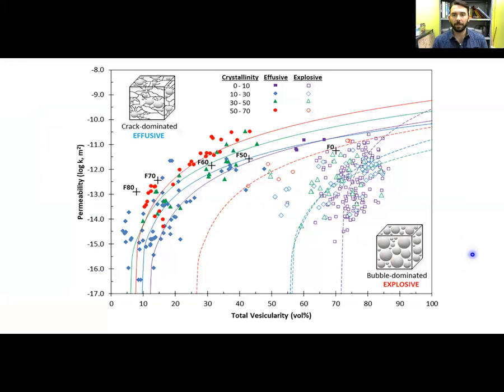Now that we've identified the outgassing mechanisms in our analog experiments, the final piece is to relate our samples to the global data set I showed earlier. In this figure of permeability versus porosity, the labeled crosses are data from this study. Closed and open symbols represent effusive and explosive data for which crystallinity was known, respectively. And these have been binned by crystal content, each with a respective color. Each bin of crystal contents was fitted using the Kozeny-Carman relationship, which calculates permeability as a function of porosity and percolation threshold. The percolation threshold is simply the minimum porosity that signals permeable outgassing can occur. Each percolation curve here, therefore, asymptotically approaches its percolation threshold.